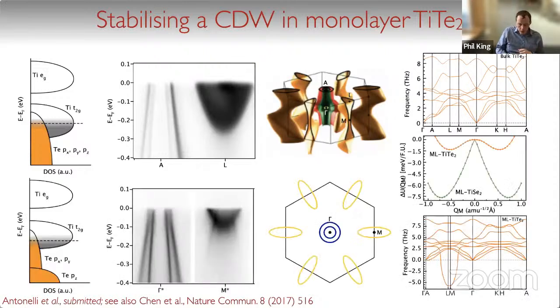But a rather surprising result from Tai-Chang Chiang's group a few years back is that if you take this material and thin it down to a monolayer, then a charge density wave phase emerges again. You can see this in our results here from monolayer titanium ditelluride, where at low temperatures we now see a backfolding of these valence states from the gamma point to the M point of the Brillouin zone, indicating a 2x2 lattice distortion has occurred at low temperatures. So it's really been a puzzling question for the last few years why this charge density wave becomes stable in the monolayer case of titanium ditelluride, while it's not stable in the bulk.